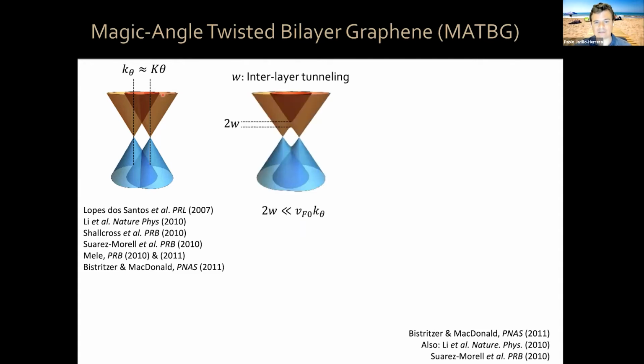So that leads to bonding and anti-bonding states, similar to the hydrogen molecule, but now in a giant graphene molecule, where this interlayer tunneling leads to a band repulsion here, to the opening of a gap. This is the situation that occurs when this crossing point of these energies is much larger than the interlayer tunneling. But as you decrease the twist angle, this crossing point goes to lower and lower energies.